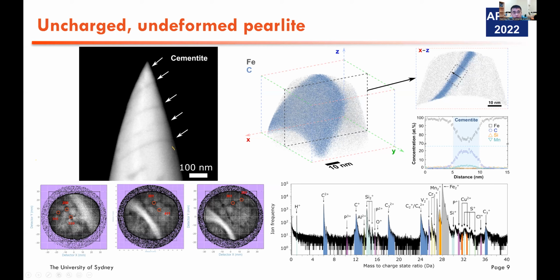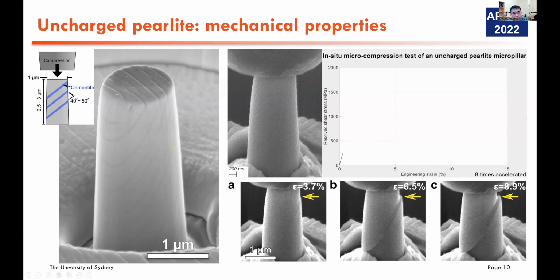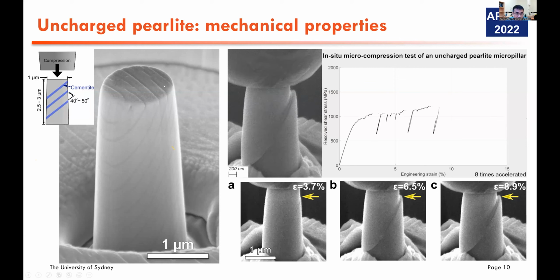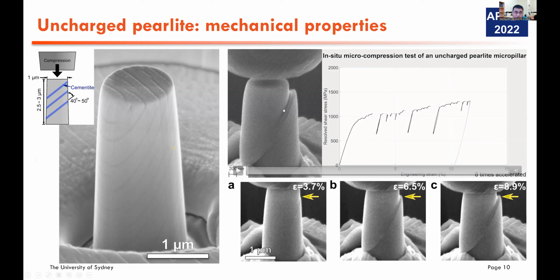So next is about the mechanical property of this interface. We prepare pillars in this orientation. All the pillars we have are prepared in 110 grains with the help of EBSD. And then we prepare the pillars with a diameter of one micron, and we place those lamellae inclined almost 40 to 50 degrees to trigger interfacial slip. And you can see during the deformation, these interfaces are slipped, and this is exactly how it looks inside the SEM.